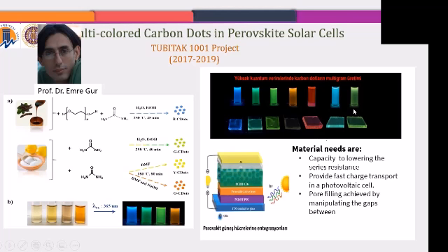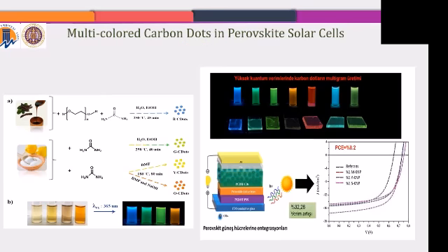We have several in here, but the 4 was chosen because of their capacity, because of their increased conductivity. And we got 8.2. It is not that high because in perovskite cells now they reach almost 20, but for this assembly, it is quite good because we had 32.26 increment in the efficiency when you compare with the reference. This was a huge outcome, and I guess we are going to have more studies on that one.